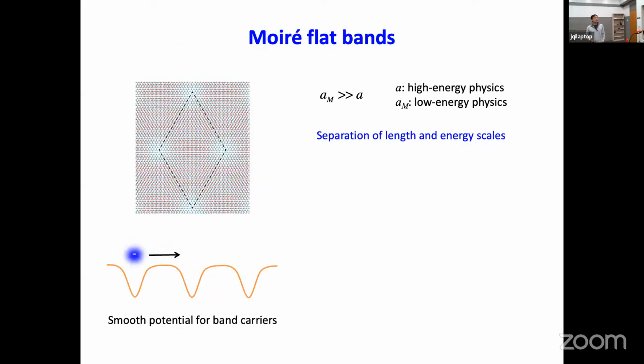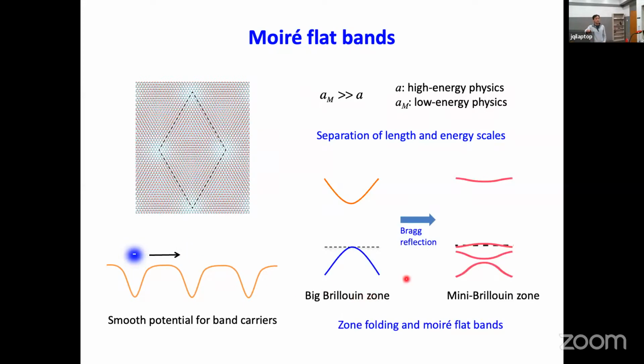Okay. And so the emergence of the Moiré length scale is nice because it's a lot bigger than the original lattice constant a. So there is a natural separation of the high energy physics, which is governed by a, and the low energy physics, which is governed by a_M here. In some sense, we can totally forget about the original lattice structure of the material and just treat the electrons, with a certain band mass from the original material, moving in this smooth periodic structure defined by the Moiré lattice. What it does is reduce the big Brillouin zone of the original monolayer material into a small Brillouin zone, the mini Brillouin zone. Because of extra Bragg reflection from this Moiré superlattice structure, a series of mini bands will be produced by this Moiré lattice.